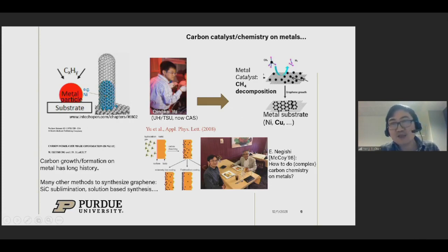In the simplest case, we pass hydrocarbon, for example, methane, on top of the nickel. Today we use copper, which works much better. And they catalyze some decomposition of these hydrocarbons. And you hope to have individual carbon atoms, and eventually they get assembled into a graphene sheet. The reality has been more complex, but this is essentially the idea or the hope.